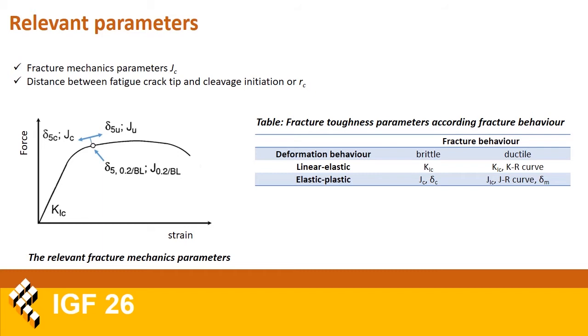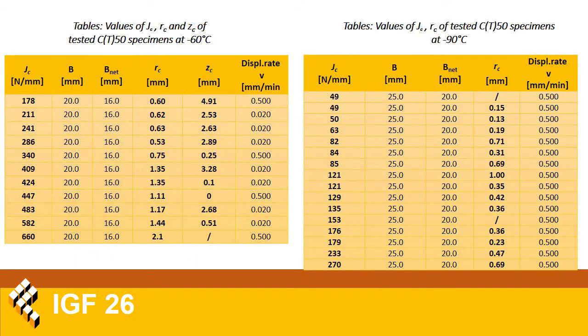It should be emphasized that this study relies on Heerens' work, and other relevant parameters introduced by him were discussed as well, such as the distance between the fatigue crack tip and the cleavage initiation, or just simply RC. Besides that, ZC, which represents the distance of RC from the medium line of the specimen thickness, was analyzed, as well as their dependence.